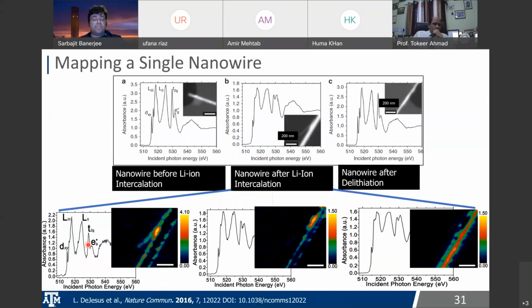Okay. So then, because we've got a very, very finely focused X-ray beam, we can image individual particles, and you can sort of see this here, right? You've got sharp dxy, t2g and eg at the oxygen K edge, and then you take a look. After lithium-ion intercalation happens, this dxy feature has gone down because the vanadium is no longer 5+; it's been reduced, and so these empty dxy states at the bottom edge of the conduction band have been filled. The t2g states are also getting filled, and so the relative ratio of t2g to eg star massively changed here, right?